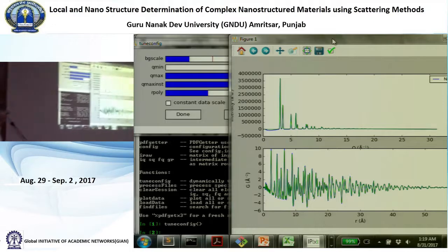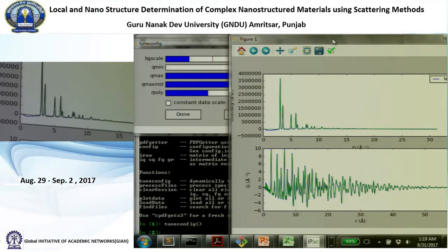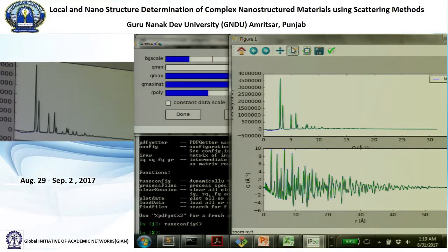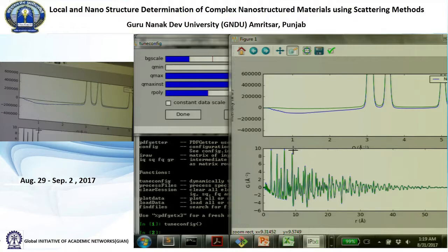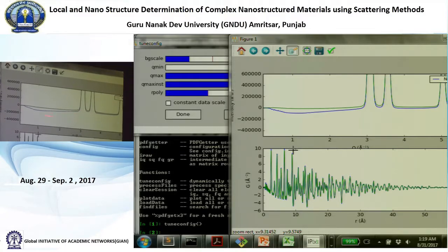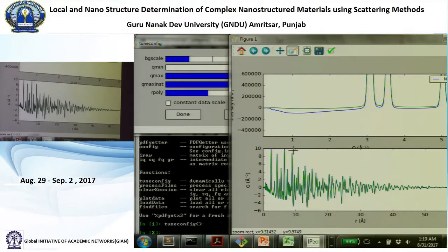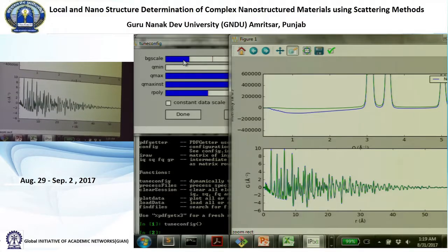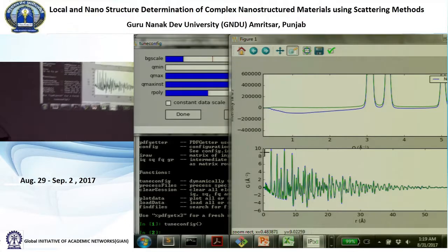And now you can see the green curve is actually kind of beautifully flat in that region. So I can expand that a little. We want to concentrate on this region here. Here I was over subtracting the background, but now the background is flat. It looks like I'm still over subtracting even a little bit, so I can move this down a tad. It gets flat like this.